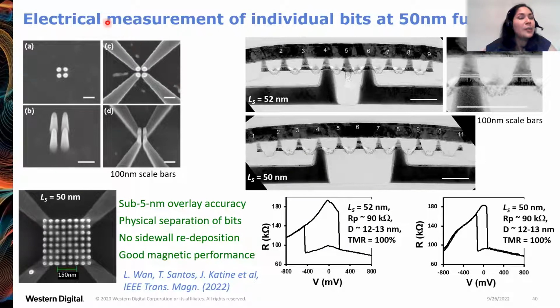Okay. On the left, I'm showing the SEM images of the bottom point contacts. This is 4 pillars, and then with the arms going out to the contact pads. And then on top of these 4 contacts, here is the MRAM array put on top, and we take a diagonal slice here to get these cross-section TEM images I'm showing.